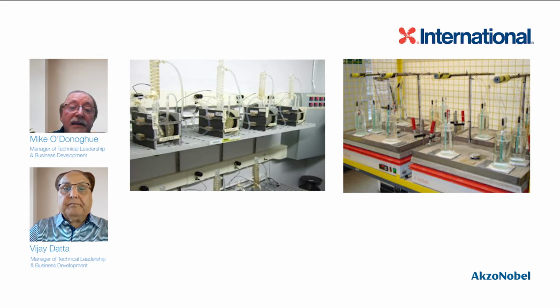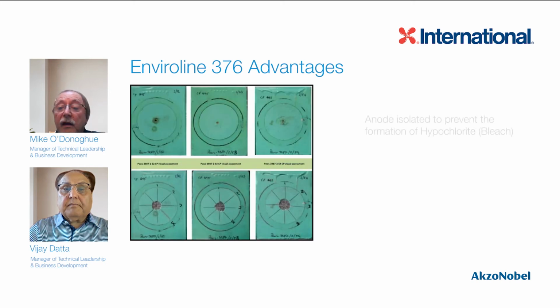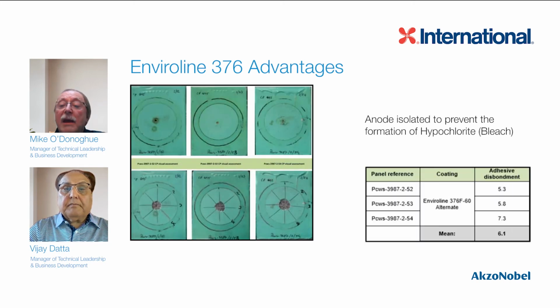In that regard, Atlas cell and CD testing is often utilized, and you see these configurations here. The Atlas cells are either pressurized or the standard Atlas cells, and then the CD testing is carried out to make sure the coatings conform to certain standards. If we look at the cathodic protection, for example, CSA Z245, we've tested the Enviroline 376 at 80 centigrade, 176 Fahrenheit, and it's showing exceptionally good small amounts of radial disbondment, far lower than the standard requires, of about 20 millimeters, but anywhere around about 5 to 8 to 9 millimeters.